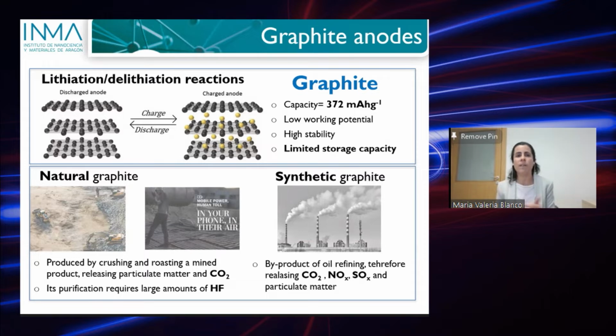In the case of synthetic graphite, it is made by using a byproduct of oil refining, which means that we are burning off hydrocarbon feedstocks and therefore releasing CO2 gases, NOx and SOx, and also particulate matter. So in this case, we are quite in a problem with using graphite as the raw material for lithium-ion batteries.